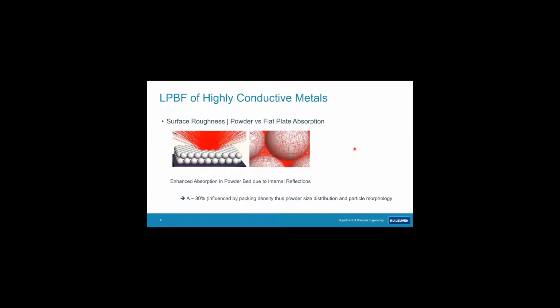One advantage we have is your laser beam does not shine on a flat surface, it shines on a powder bed and on a melt pool. So for a powder bed, it has been shown theoretically, and I should mention a reference here, that the laser absorption is enhanced due to intrinsic scattering in the powder bed itself, up to a factor of 6 or less for copper. So that meant for a near-infrared laser 30% absorption in a powder bed.